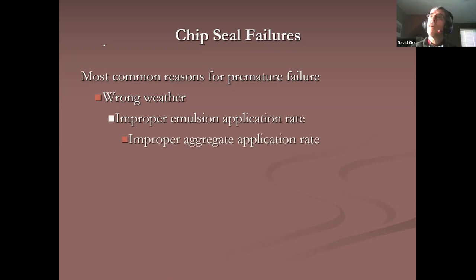Somebody here says our policy is to wait no more than a couple hours to sweep the chip seal because of liability with vehicle damage. If you're not using too much down pressure, you can probably get away with that. Be careful that you don't over sweep and actually reduce the coverage by the stone. I can understand that policy, but just be careful you don't damage the chip seal. And then number four, placing the stone too late. What I mean by that is the spacing between the spreader and the distributor: keep them close to each other.